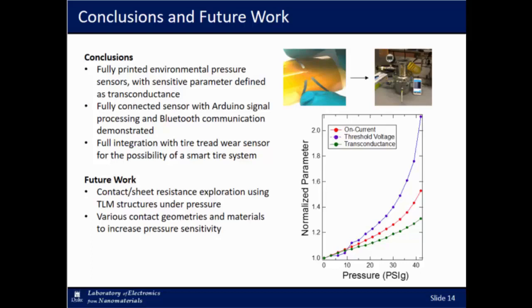For future work, we need to do a lot more work on identifying the mechanisms. And so we plan to do this by designing structures in which we could extract the contact and the sheet resistance by printing multiple channel lengths and using transmission line models to extract those values to really gain more understanding. Is it the sheet resistance that's changing, the contact resistance, or that electrostatic control that's based on the dielectric? So that's the future work. We also plan to look at different geometries and further explore the hysteretic effects.